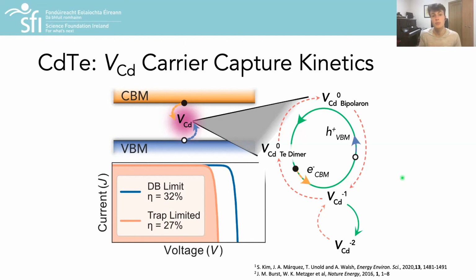In fact, the 1 volt open circuit voltage threshold for cadmium telluride solar cells was recently broken by Burst et al., which required breaking the mold by shifting toward an unorthodox strategy of cadmium-rich stoichiometry and anion doping, reducing the formation of cadmium vacancies as well as tellurium and cadmium antisites.